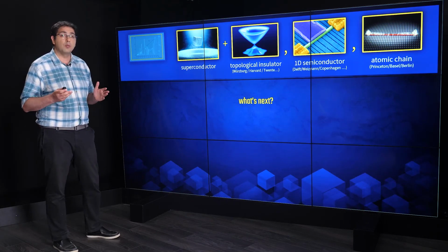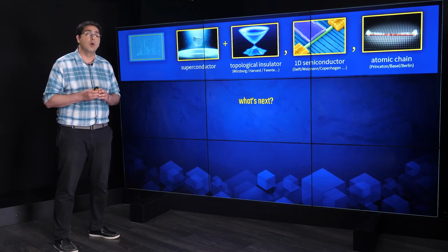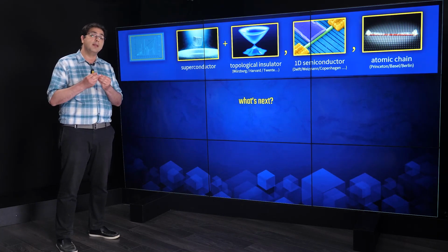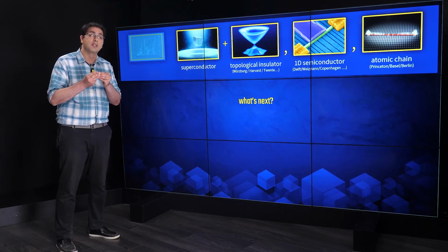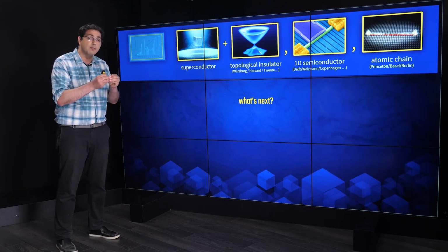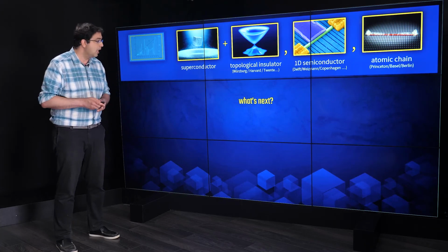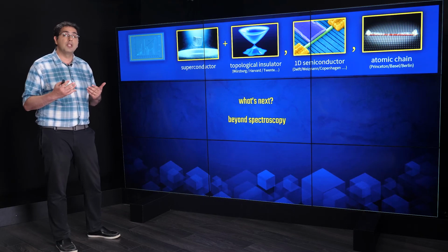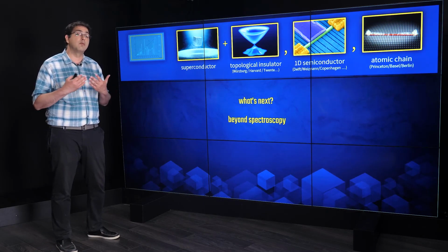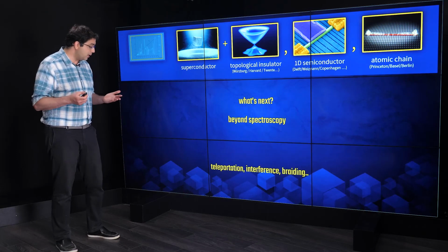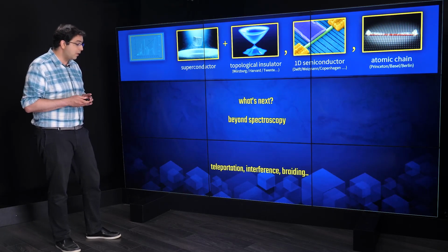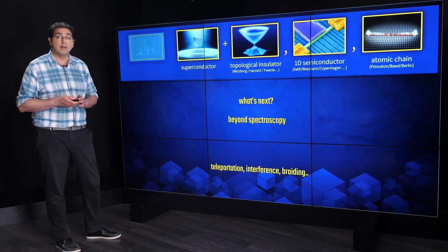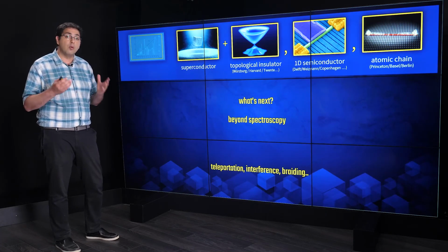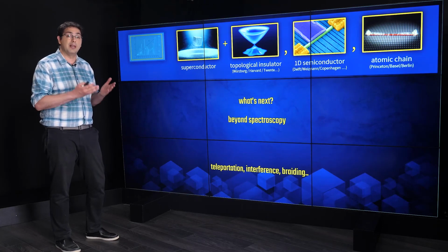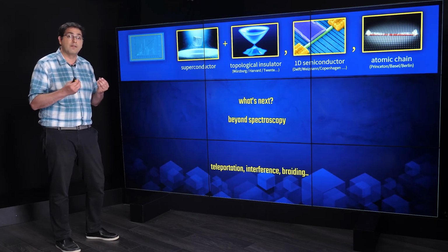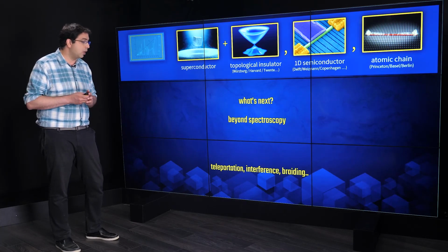In all of these measurements, the main thing that we showed was a zero bias peak measurement, where we are looking at the degeneracy of the ground state by looking at the zero bias peak. And what's next? Something which is beyond spectroscopy. We want to see something which is more than a zero bias peak measurement. And by this I mean, for example, a teleportation experiment, an interference experiment, or braiding. Braiding is the only thing that in the end will show us that we actually have non-abelian quasi-particles that have characteristics of non-abelian statistics, and this is really what we are after.